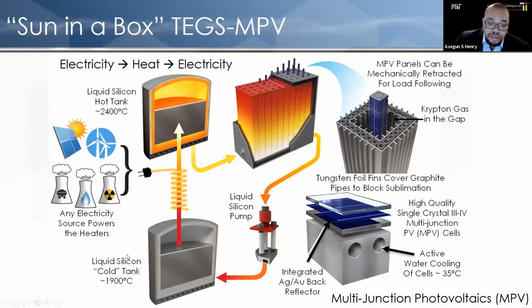We're essentially doing 2-tank thermal storage, but our low temperature is actually like 1900 degrees C, so our quote unquote low temperature. And the high temperature is like 2400 degrees C. So we take electricity off the grid and heat up the medium. In our case it is actually liquid silicon, similar to Alejandro's case, but instead of using a phase change, we're using it as a sensible heat medium, stretching it over a delta T of about 500 degrees C. We heat up the liquid silicon, store it in a hot tank, and then when power is desired, run that through a heat engine, which again, similar to Alejandro's case, is photovoltaic cells.